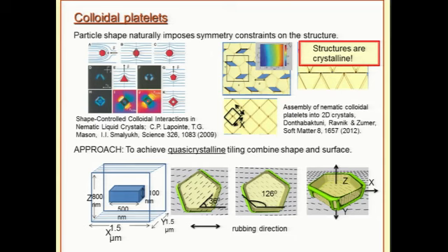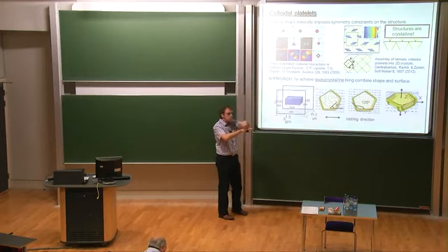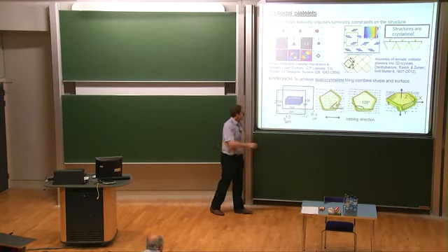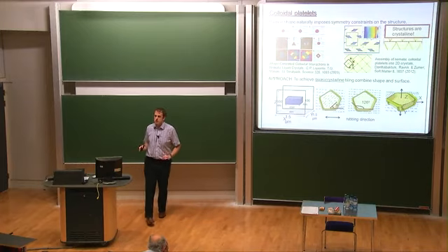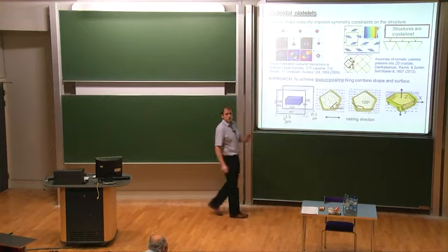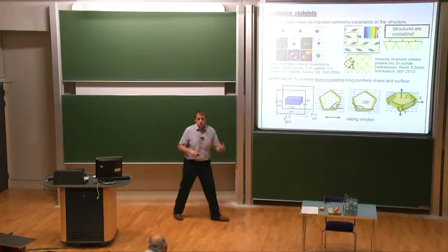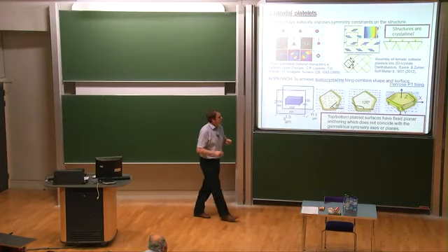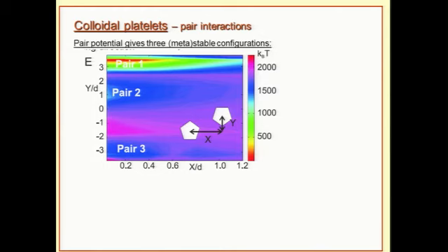So that means not degenerate, uniform. But the top and bottom surfaces must be misaligned. They will be at some angle, one with respect to another. Here I have some magic number, 36. It can be also some other, but they shouldn't be along some of the symmetry directions. Some directions are forbidden. And these are the structures which, I'll show you, can actually build a Penrose P1 tiling. If you can build a Penrose P1 tiling, that's a material with quasi-crystalline symmetry.